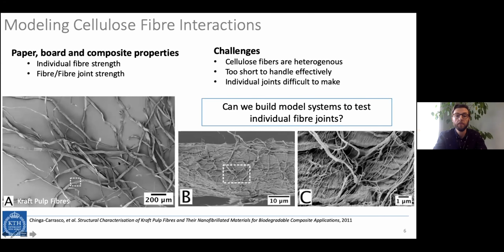And so the process that we've chosen to do is to make model filament fibers. Some of you may have seen this before, but we use a flow focusing system where we have cellulose nanofibers along the core and HCl on the outside of an extruder. As we extrude this material into an HCl bath, the CNFs coagulate and form a fibril.